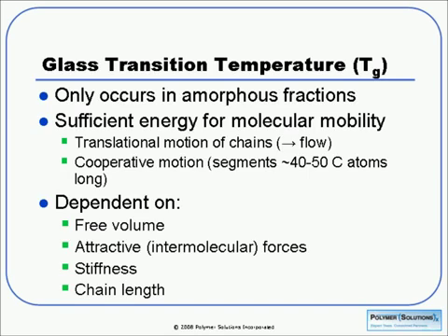The temperature that this occurs at is dependent on several variables, things like free volume, which is simply the area between chains, attractive intermolecular forces like hydrogen bonding, the stiffness of your backbone, chain length or molecular weight. And I do want to say here that when I'm talking about putting energy into our samples, for our purposes, basically that means heating them up.